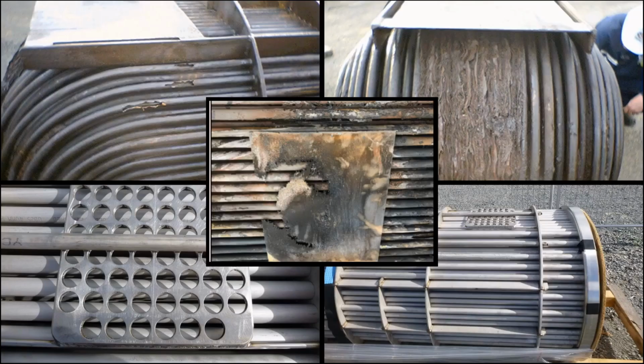20 years later, we came across exactly the same problem. Tube failure that was diagnosed as erosion corrosion. In the upper pictures, we can see a welded plate that was installed to protect the tubes. And within 6 months of starting up the plant again, you can see the severe corrosion that occurred below that welded plate. The bottom two pictures show another facility that also had corrosion and decided to install a plate, but did follow through with the guidelines to drill holes in the plate to dissipate the energy, but also keep those tubes properly wetted. And that was successful in achieving a long life.